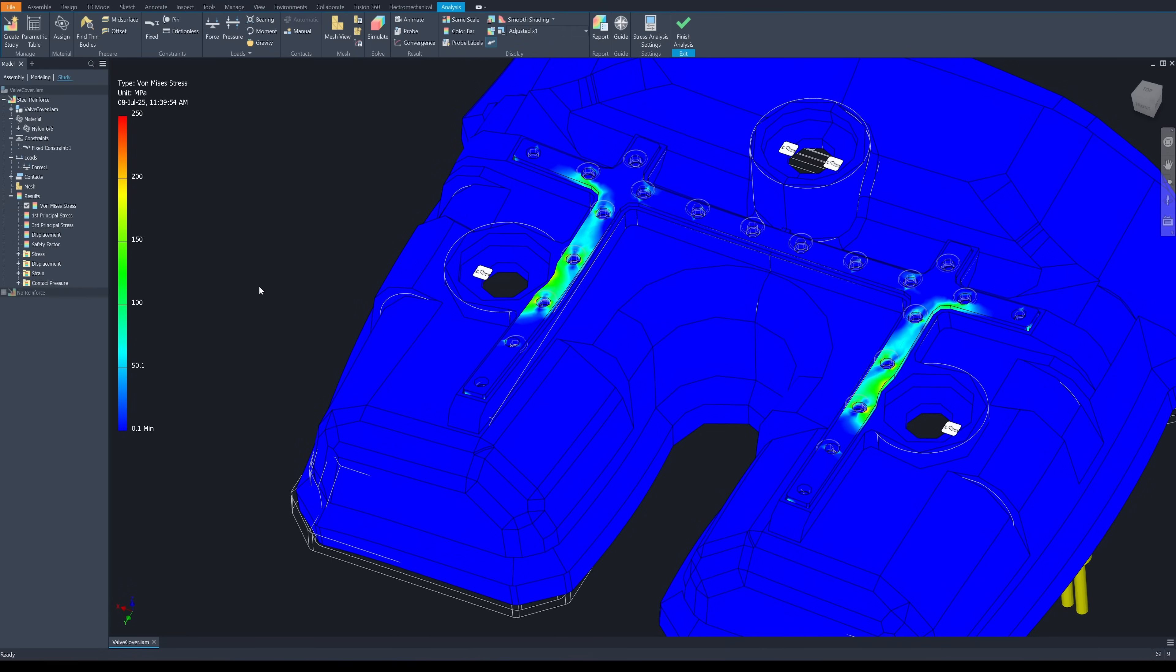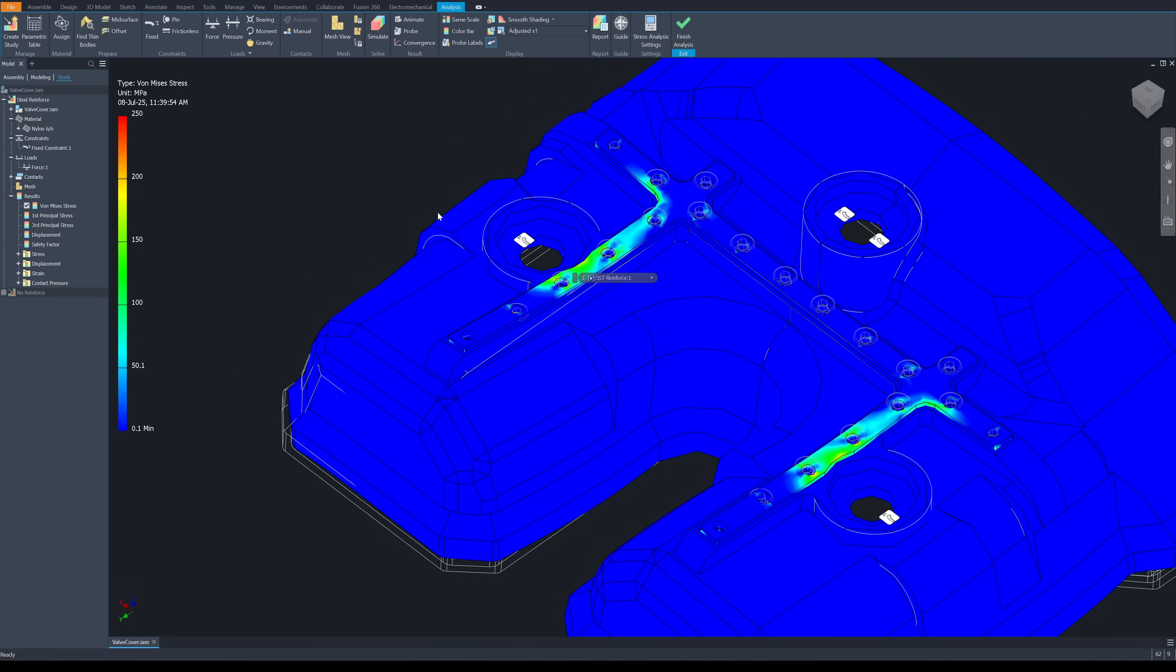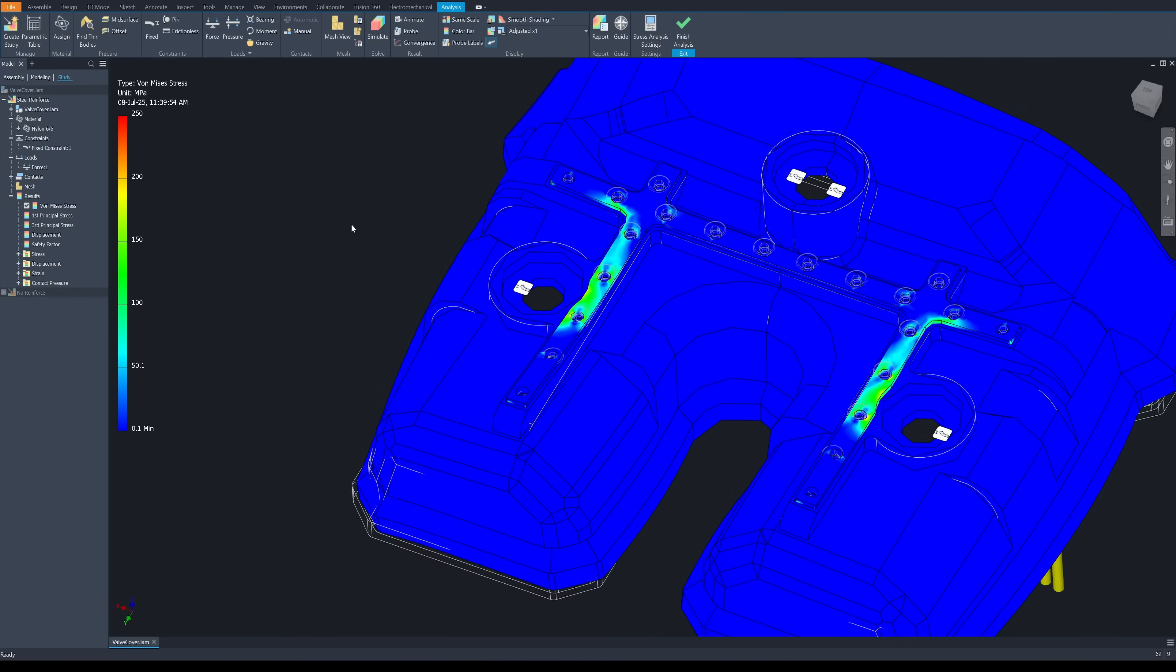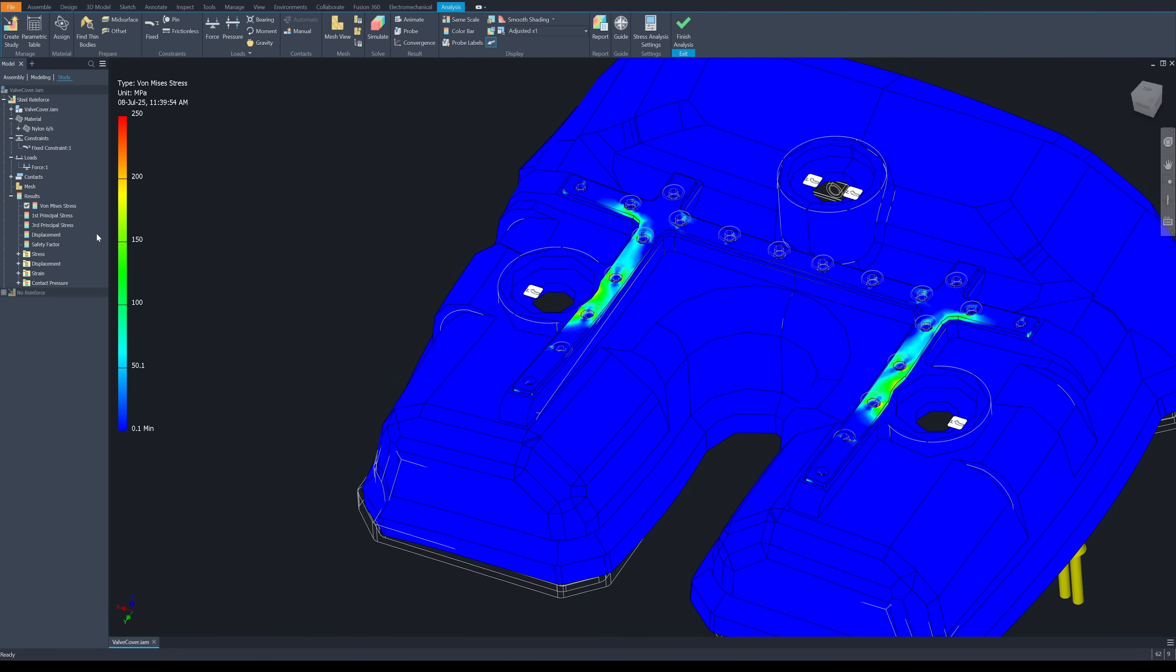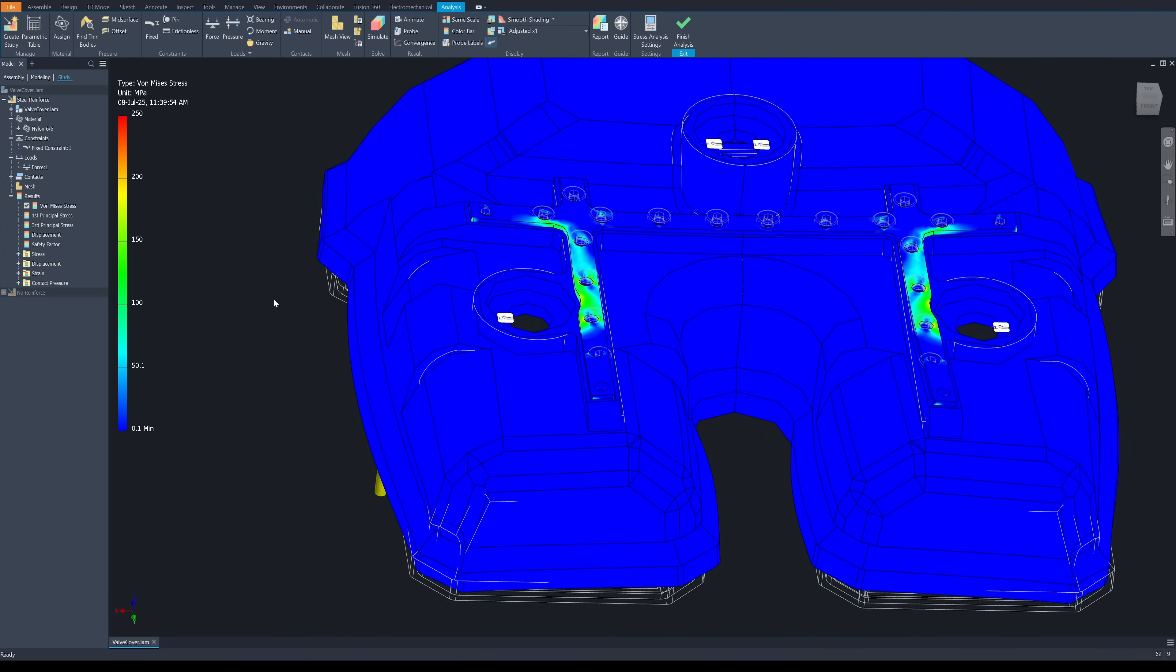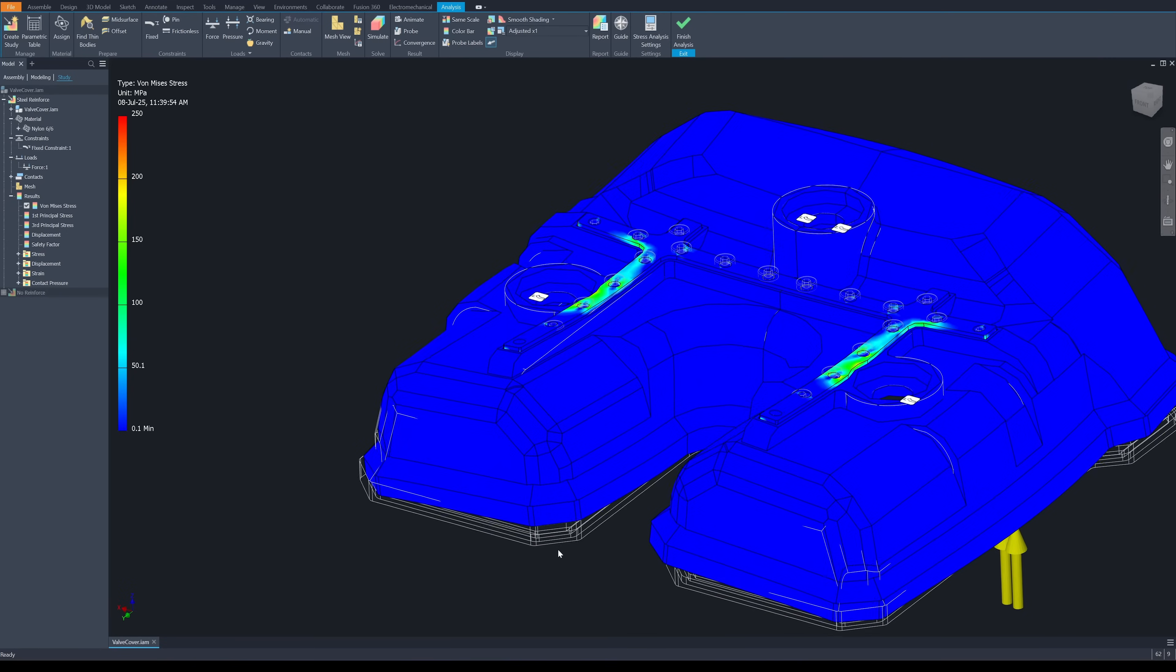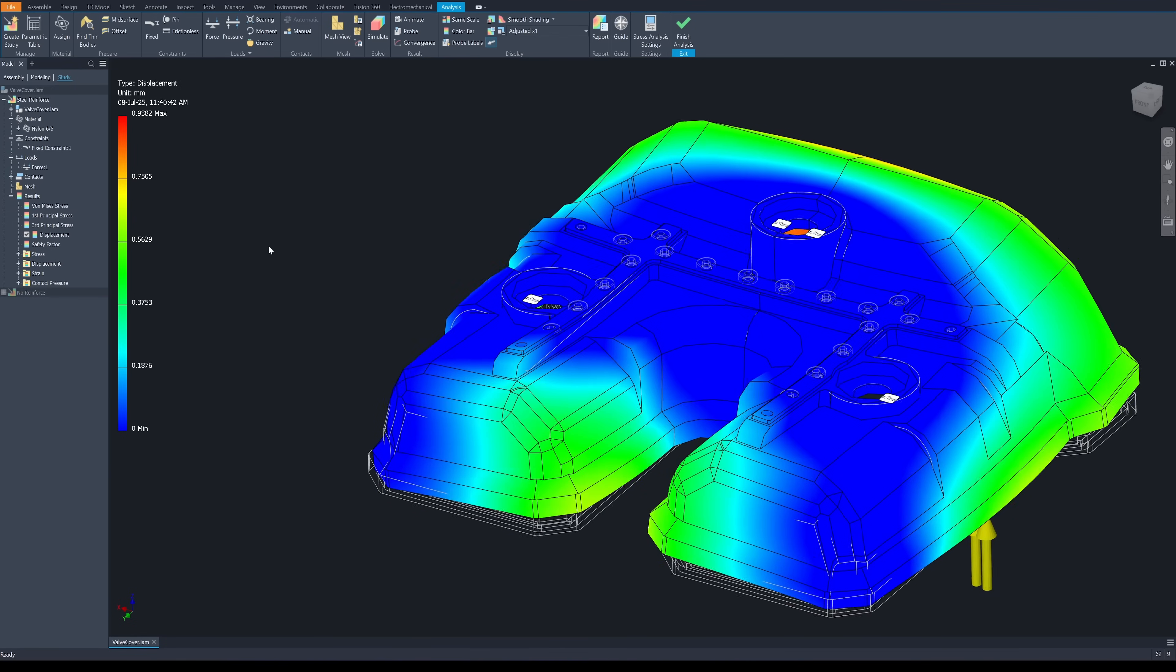Okay, now with 100 kg, the 2 mm steel plate has a stress of only 150 MPa, which is below the yield point, 250 MPa of stainless steel. So the stainless steel will carry all the load. If I pre-tension the 3 bolts less than 100 kg, then the stainless steel can carry all the load without help from the nylon shell.